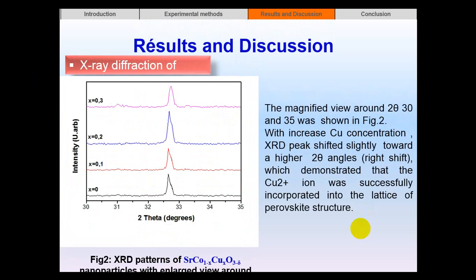The magnified view around 2 theta 30 and 35 is shown in figure 2. With increasing Cu concentration, the XRD peak shifts slightly toward higher 2 theta angles, a right shift, which demonstrates that the Cu2+ ion was successfully incorporated into the lattice of the perovskite structure.